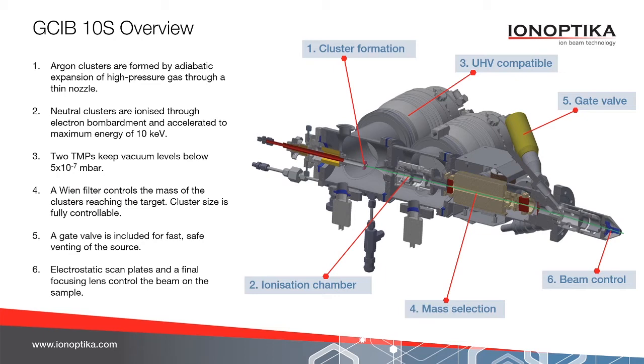So to give you an overview of how the GCIB 10S works, this is a cut through of a typical system. It's a very simple system, really. The clusters are formed in what we call the expansion chamber. High pressure gas passes through a very thin nozzle into a low vacuum region. This results in adiabatic expansion of the gas, which causes it to cool and form small clusters. These clusters can range anywhere from argon 2 to argon 5000 and more.